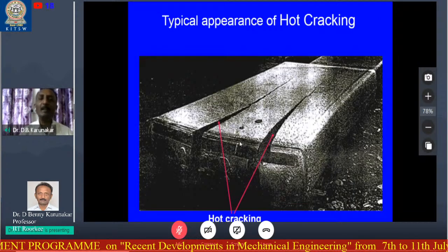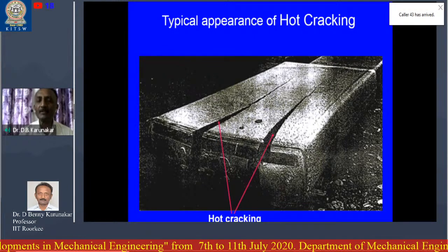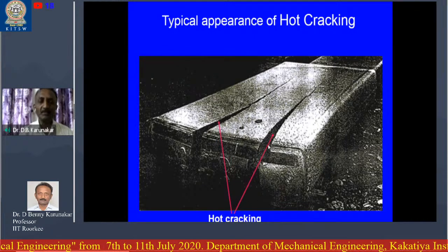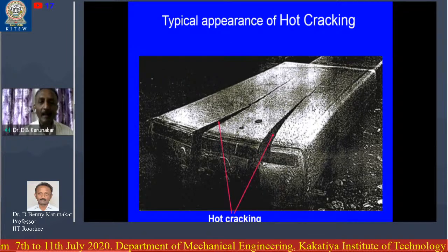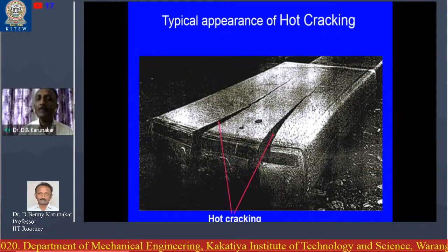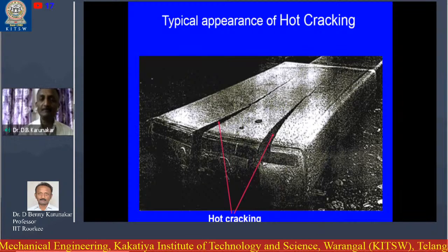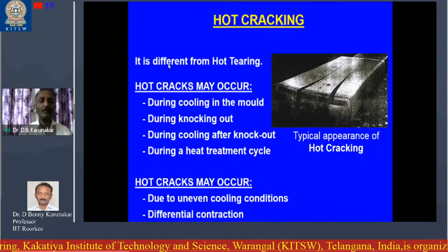Generally this hot cracking arises for very large castings. You see, this is a big casting, so there is a crack, and this has arisen after solidification, not during solidification. What are the reasons?